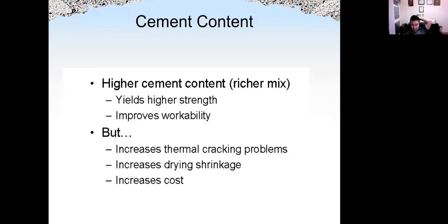For cement content, if we increase cement content, it will generate higher strengths, because for the same water cement ratio, we have a better workability and better compaction also. But higher cement content will increase potential for thermal cracking, and also increase drying shrinkage and autogenous shrinkage, because only cement paste will shrink, aggregate will not shrink, and also, of course, the cost will also be